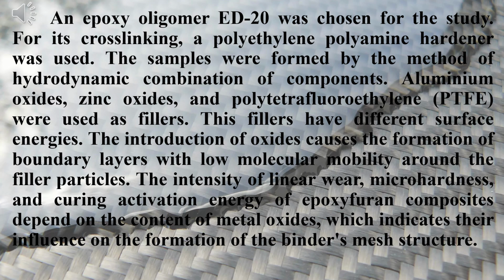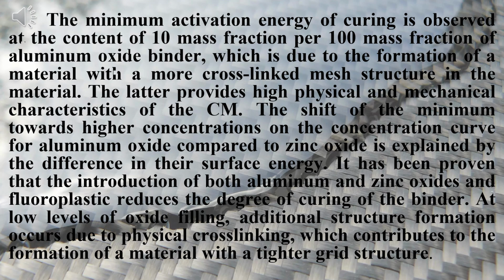The introduction of oxide causes the formation of boundary layers with low molecular mobility around the filler particles. The intensity of linear wear, microhardness, and curing activation energy of epoxy composites depend on the content of metal oxides, which indicates their influence on the formation of the binder's mesh structures. The minimum activation energy of curing is observed at the content of 10 mass fractions per 100 mass fractions of binder of aluminum oxide, which is due to the formation of a material with a more cross-linked mesh structure. The latter provides high physical and mechanical characteristics of the composite material.